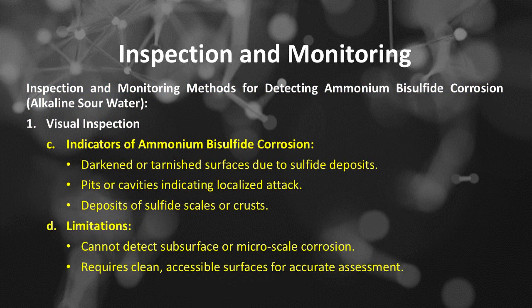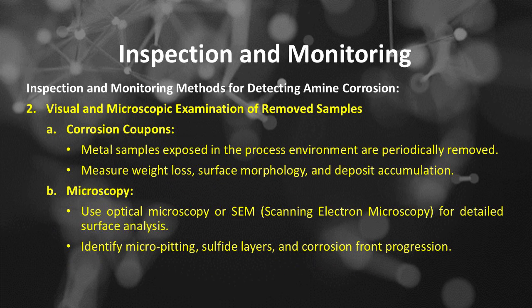The indicators of ammonium bisulfide corrosion include darkened or tarnished surfaces due to sulfide deposits, pits or cavities indicating localized attack, and deposits of sulfide scales or crusts. The limitation of visual inspection is that it cannot detect subsurface or microscale corrosion, and it requires clean, accessible surfaces for accurate assessment.